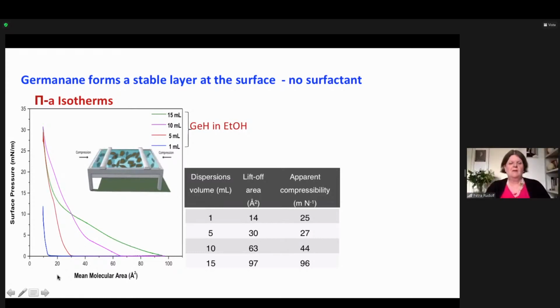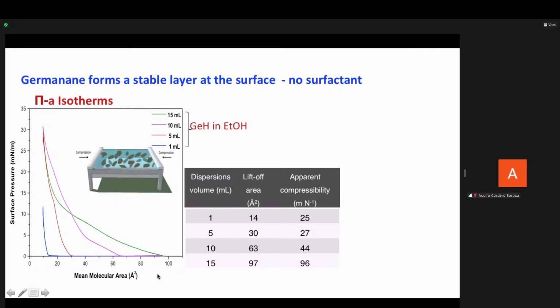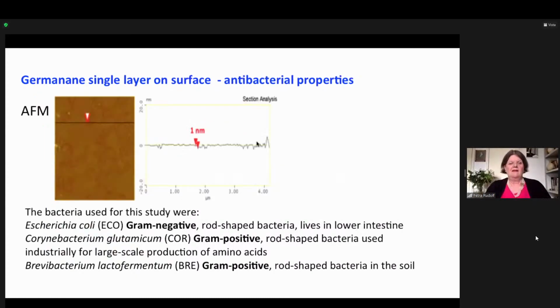Depending on how much material you put on the surface, you get the transition from a 2D gas to a 2D solid or liquid at different pressures. So you get a stable layer. At the surface, you don't need any surfactant. And here you see, I don't know if you can see, the contrast is not very good, but you have the little flakes which touch each other. And if you measure the distance, you see that the flake is 1 nanometer in height, which is what you would expect if there is some water on top. So that is what you expect to get.